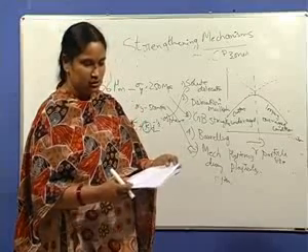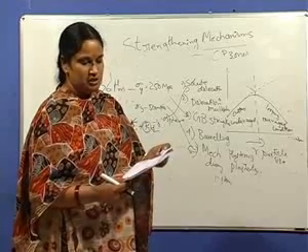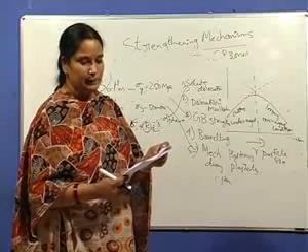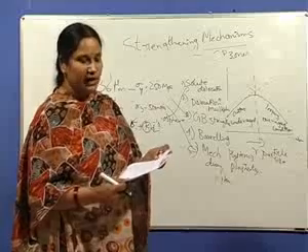And one more is with respect to dispersion strengthening that I have discussed in today's class. Identify the attributes associated with dispersion hardened alloys. First option is dispersoids do not dissolve in the matrix even at higher temperature. Second is dispersoids are coherent with the matrix. That is wrong. Third is dispersoids impart creep resistance to the alloy. That is correct. And fourth is dispersoids improve the corrosion resistance of the alloy. So the attributes are the first and third option.